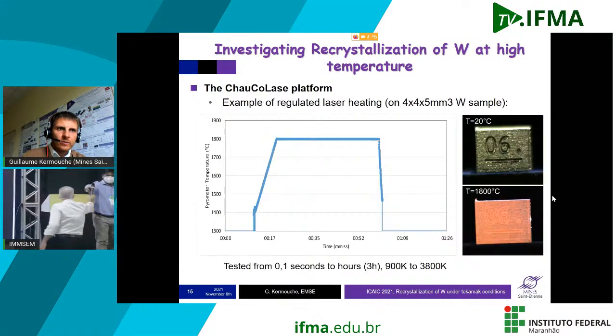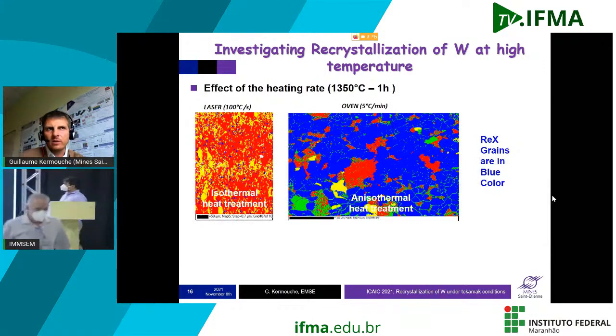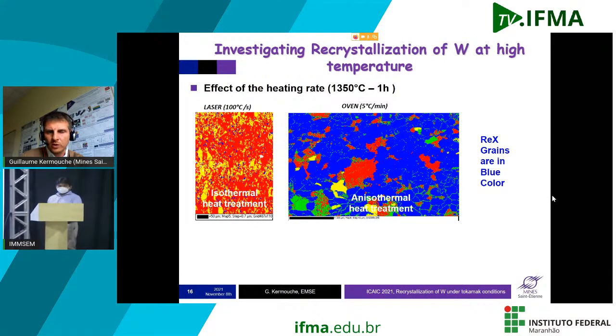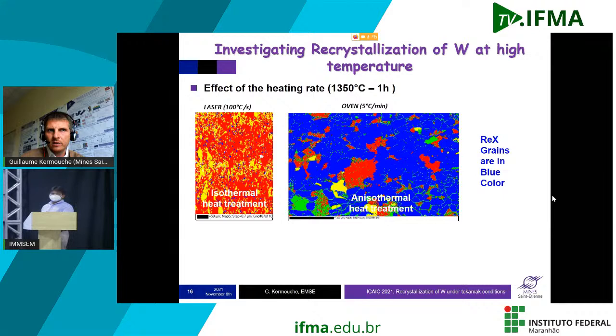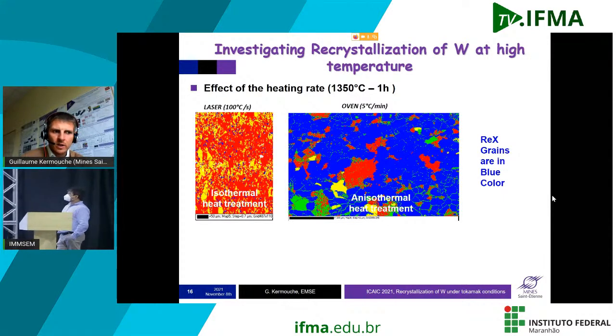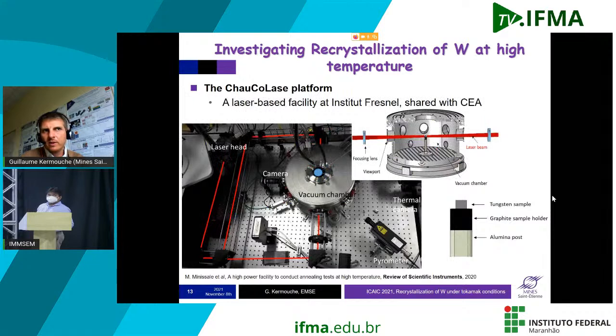Okay. So with a furnace oven, most of the time the heating rate is quite low. You can use some specific furnace that can go to higher heating rates, based on induction, basically, or we can use resistive heating, but in the case of tungsten, for us, it was easier to use a laser heating setup, with some pyrometer and thermal camera to regulate the heating. So that's why we chose that. And in a way, for us, it was simpler than using another kind of heating device. We tried induction, it was not so easy. So that's why we moved to that. And now it works quite well, so it's not so complex.